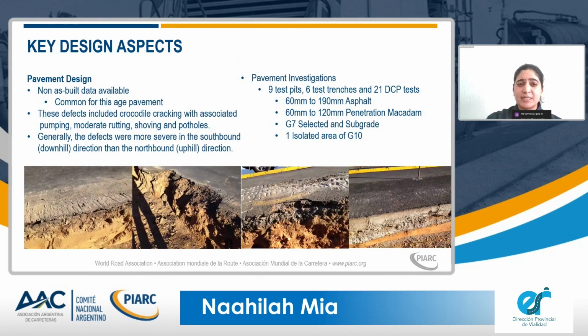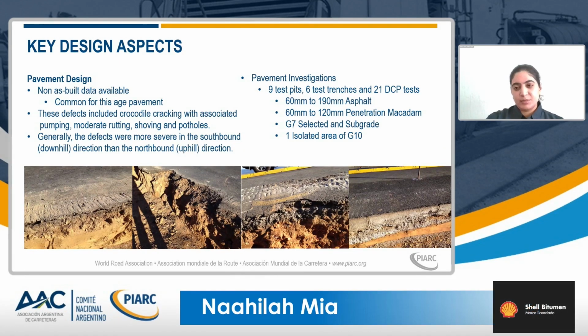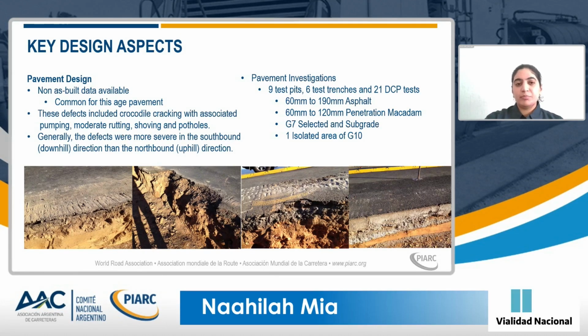The pavement design. There was no as-built data for this pavement, which is normally common for the age of this pavement. The defects on the road included crocodile cracking associated with pumping, moderate rutting, shoving, and potholes. Generally, the defects were more severe downhill than they were uphill.